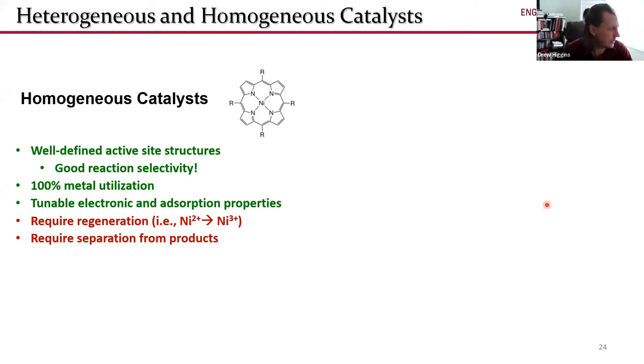Another big advantage of this is that you can achieve 100% metal utilization. When the active site is in ionic form, that means there's just one transition metal site that's doing the catalysis. In the case of a nanoparticle, you're going to have hundreds, thousands, tens of thousands of atoms all together in a nanoparticle. A lot of those are going to be in the bulk of that nanoparticle, and they're not going to be available to do the catalysis. So you're essentially paying for metal atoms that are not doing any heavy lifting in terms of catalysis. With structures like this, in principle, every single one of your transition metal atoms that you're paying for and you're putting into your catalyst can be available to do the catalysis. So in principle, we can achieve 100% metal utilization.